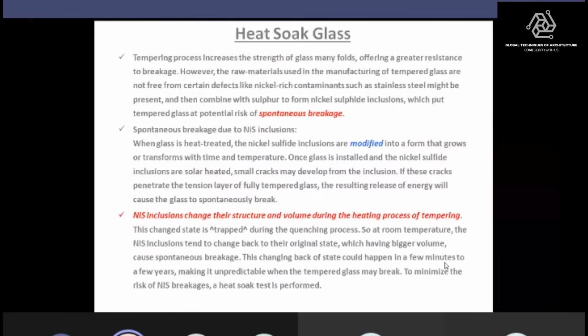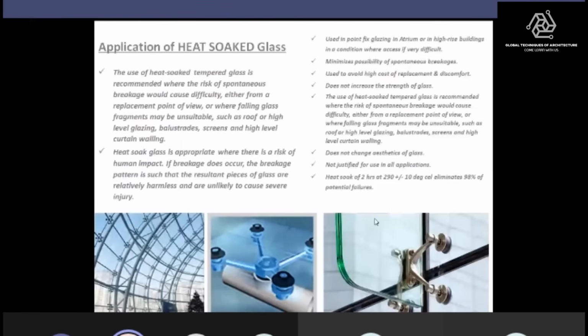So you can see the tempering process increases the strength of glass manifold, and because of the spontaneous breakage, when glass is heated, nickel sulfide is formed. But when this glass is heated again, inclusions are modified into a form that grows and transforms. Nickel sulfide can change structure and volume during the heating process. So whatever happens in this heat soak in the furnace gets you the perfect glasses out of it. But of course, it's a costly affair. So where do we use this heat soak test? Heat soak glass is to be used when there is overhead glazing. Wherever there is a glass fin system like this, you have to use heat soak for this part, because this part is a structural member.